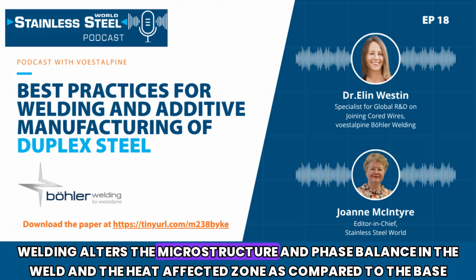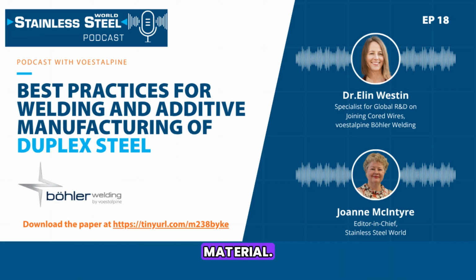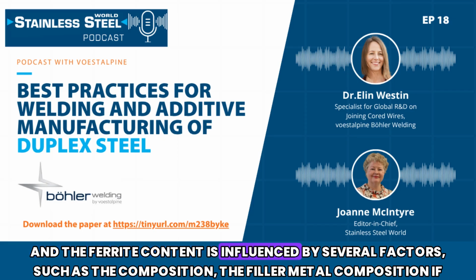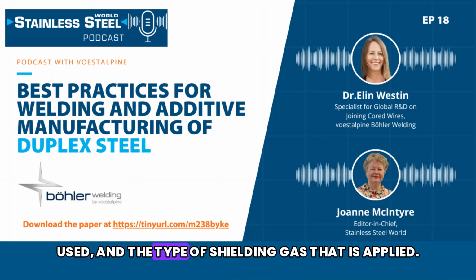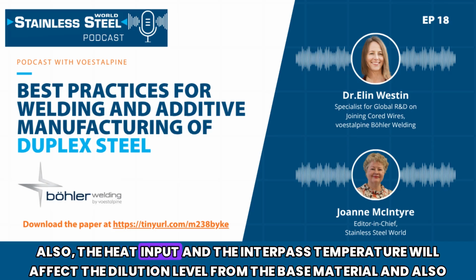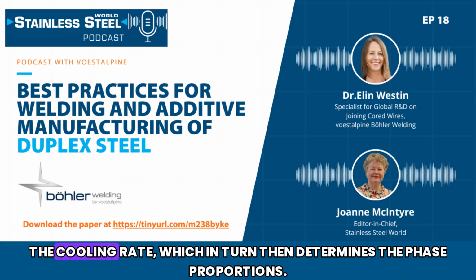Welding alters the microstructure and phase balance in the weld and the heat affected zone as compared to the base material. And the ferrite content is influenced by several factors, such as the composition, the filler metal composition, if used, and the type of shielding gas that is applied. Also, the heat input and the interpass temperature will affect the dilution level from the base material and also the cooling rate, which in turn then determine the phase proportions.